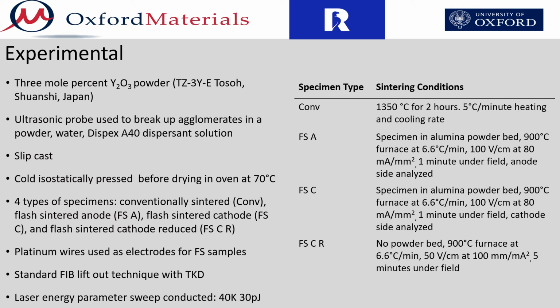YSZ specimens for APT analysis were sintered using commercially available Tosoh powders. Pre-sintering powder processing includes ultrasonic agitation to break up agglomerates, slip casting into a suitable geometry, and cold isostatic pressing before being placed into a furnace for sintering. 4 different types of specimens were studied. Conventionally sintered specimens were analyzed as a baseline.